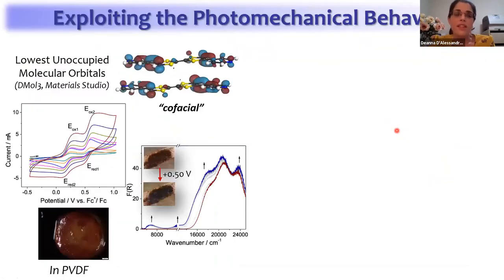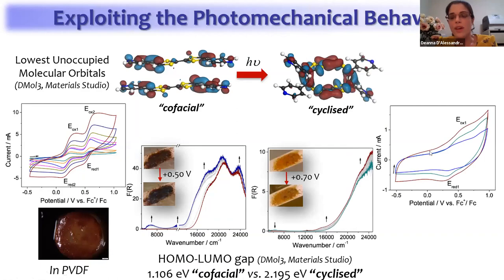Now, what is interesting is the connection between that photocyclization and the electrical and optical properties. So here we see the electrochemistry of the cofacial system itself, and we see the TTF undergoing oxidation by one and two electrons. We also see that characteristic near infrared band due to intervalence charge transfer. But when the system photocyclizes, what we see is that we actually lose the radical character, if you like, of the tetrathiafulvalene, and there is actually no observation of intervalence charge transfer.